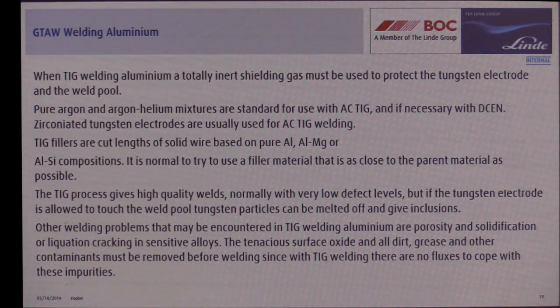But if the tungsten electrode is allowed to touch down in the weld pool, you're going to get contamination in the weld. So it's very important not to touch down the tungsten. Once it's contaminated, you can't use the tungsten again. It's very difficult to get a stable arc once you've touched that tungsten down. Other welding problems are liquation cracking. As we said before, it's sensitive alloys and that tenacious oxide. Any grease or oil, as has been said before, is not conducive to a good weld.